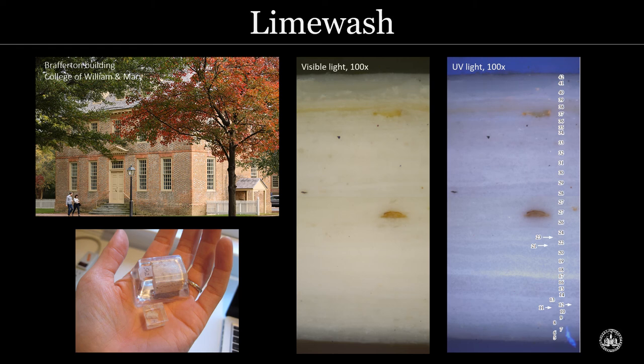And the interpretation of samples is hard too. So in these images on the right side of the screen, these are cross sections taken from lime washes in the Brafferton building on the campus of William and Mary, which is also located in Williamsburg. It's kind of one of our sister institutions. And there were so many layers of lime wash applied to the inside of this building, and they had no dirt separating them to amplify those interlayer boundaries. Just so many layers of lime wash. So I really had to rely on ultraviolet light to really bring attention to the boundaries between those layers and to be able to count all of the lime wash layers. So analysis of lime washes is very challenging.